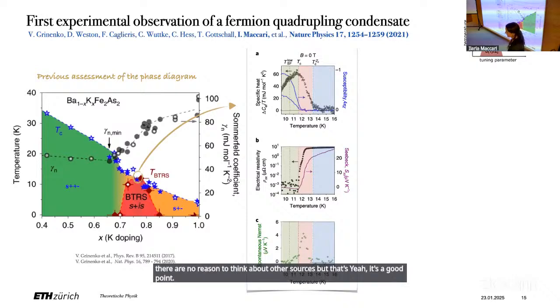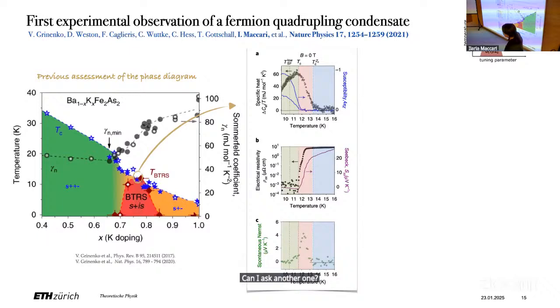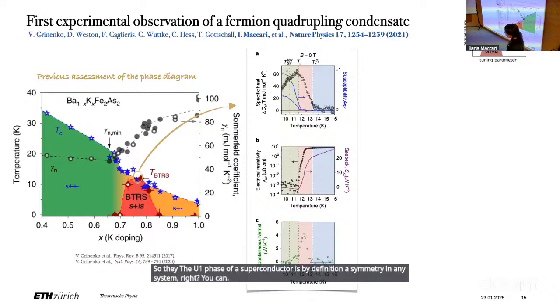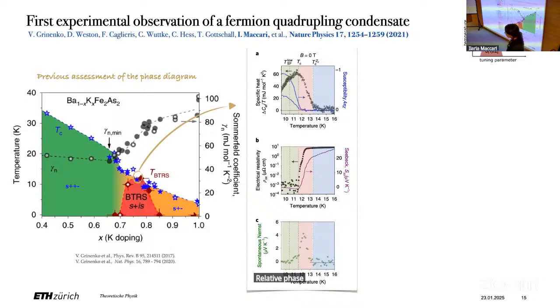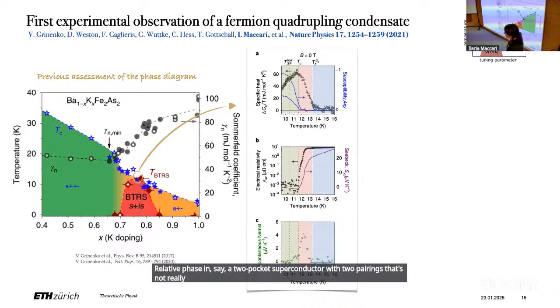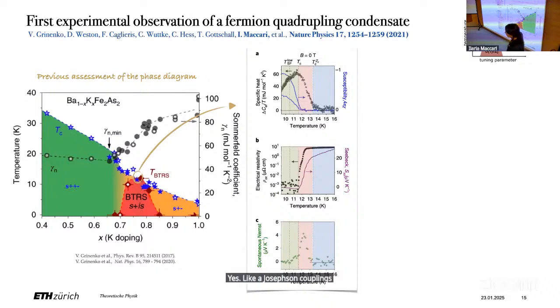Can I ask another one? This is a more basic one, I guess. The U(1) phase of a superconductor is by definition a symmetry in any system, right? Even without pairing, you can do this U(1) transformation, and that's always a symmetry. The relative phase in, say, a two-pocket superconductor with two pairings is not really a fundamental symmetry. You can cook up terms that pin the relative phase. Yes, like a Josephson coupling, or some interband coupling, even without the attraction in the superconducting channel.